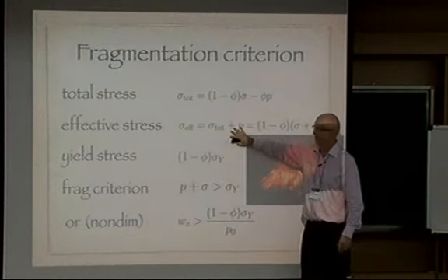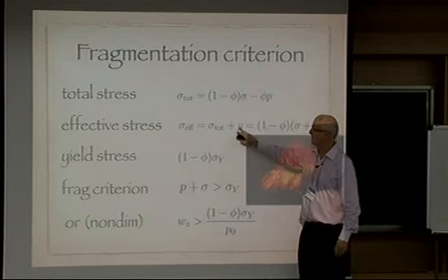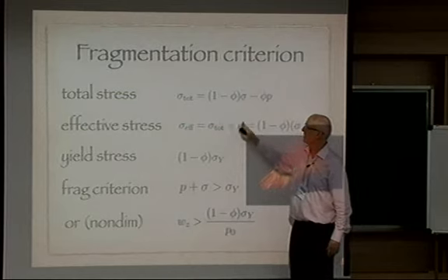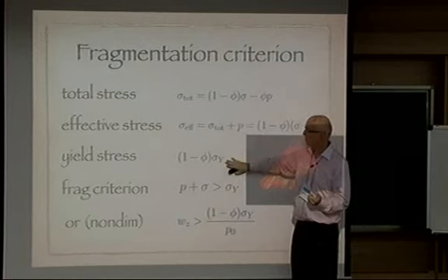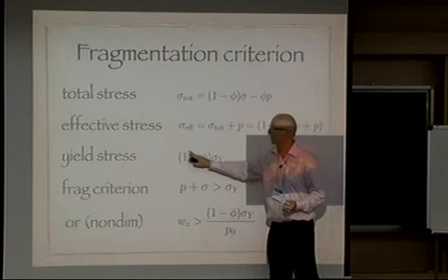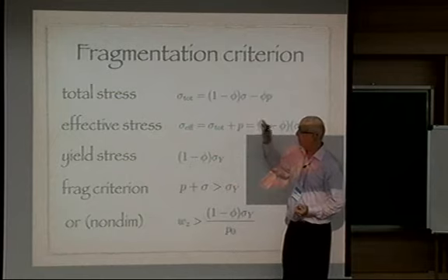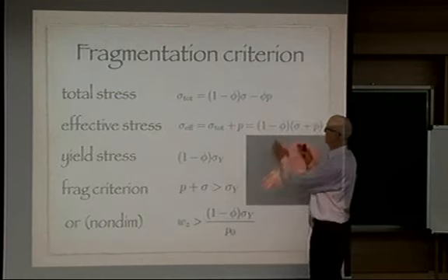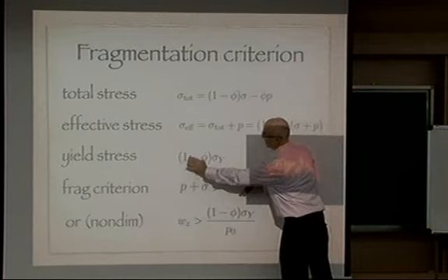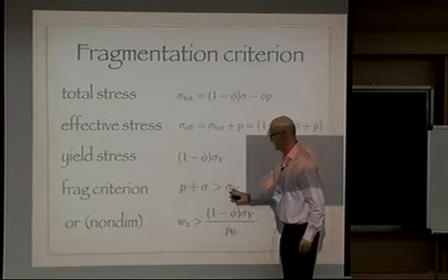For that we need to worry about when it breaks. We'll use some ideas from soil mechanics to give an effective stress, which is a combination of the total stress and the pore pressure. Then they have a yield stress, which is the tensile strength modified by the porosity of the rock. We say, right, when the effective stress is greater than the yield stress, and this is greater than this, you can cancel out by 1 minus phi, so p plus sigma is greater than sigma y.